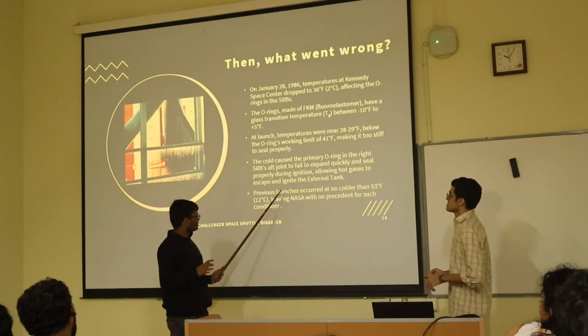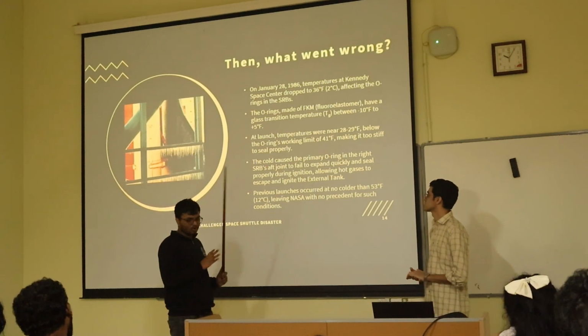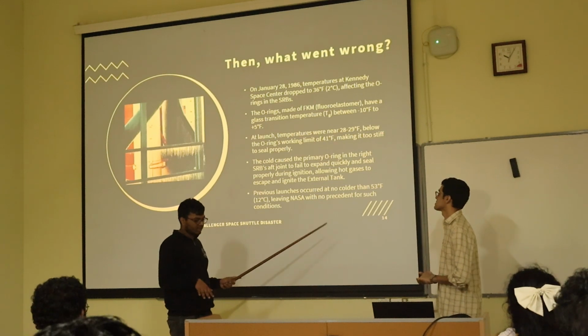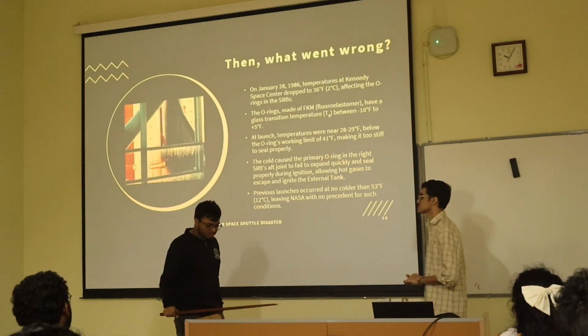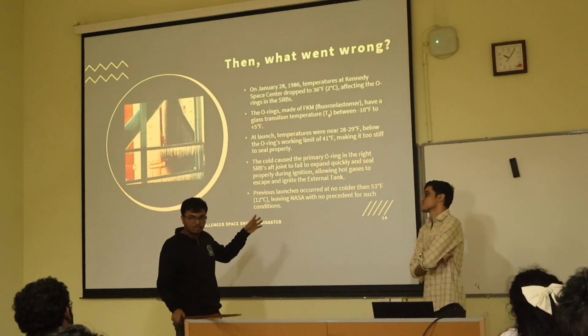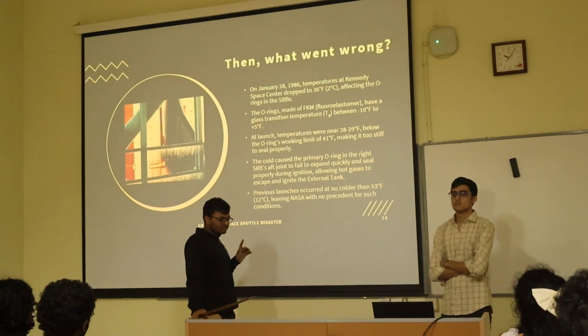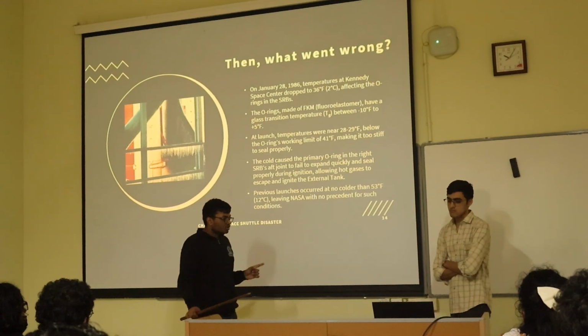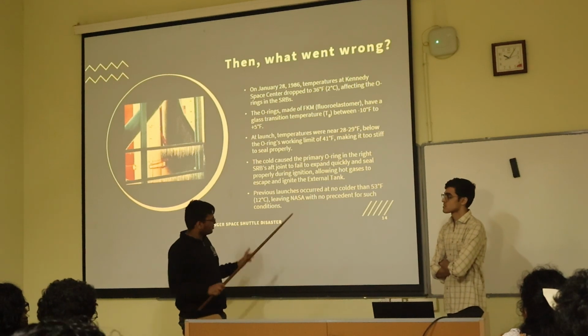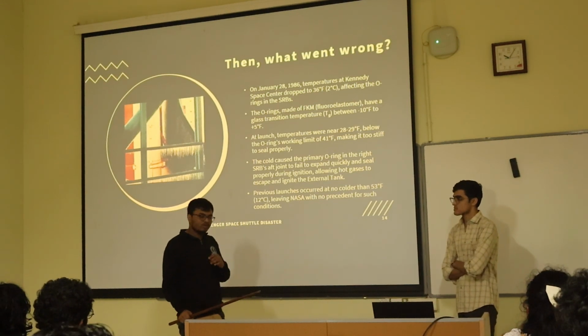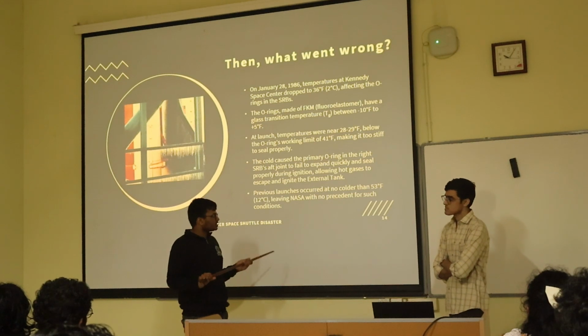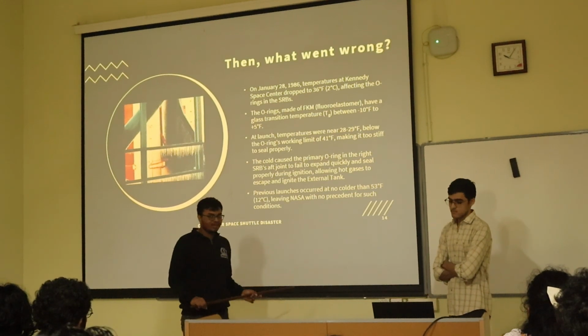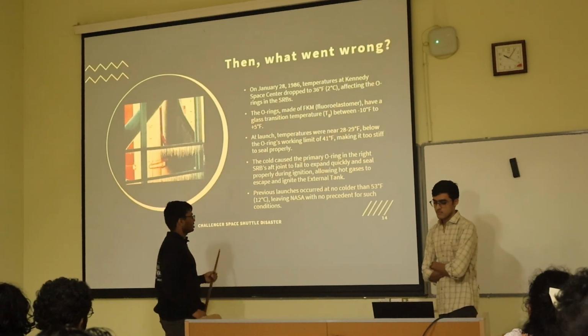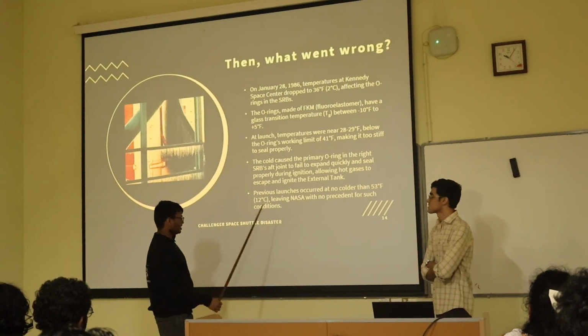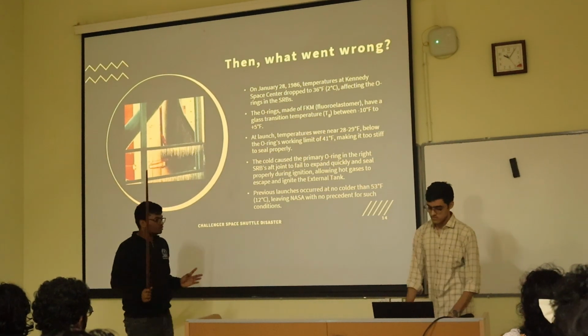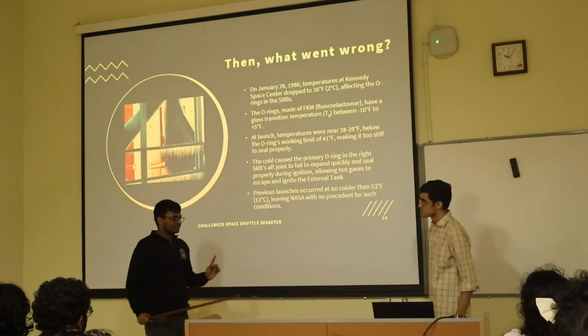Now, any of the launches before this were not colder than 53 degrees Fahrenheit. And this was actually the previous year, STS 51-C. At that 53 degrees Fahrenheit, one of the primary rings failed. They somehow managed to survive with just the secondary rings. If that had not taken place, we would have had a worse casualty. So, not many options.